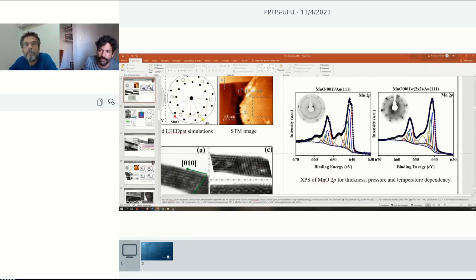From the electron occupation rule, right? So then you have more intensity in one than the other one. And then you know that this ratio should be respected. So in this case here, one is half of the other one. So now you also know that, for instance, for the 2p, when you create this hole in the atom, you don't have a neutral atom, you know that it's in an ionic state.